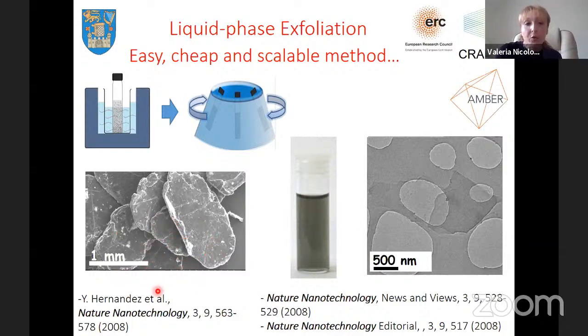So what we were capable of doing, and this goes back to my first postdoc work, was really applying everything we had learned for my PhD thesis. We had learned it for carbon nanotubes, but we applied it to layered graphite. We took commercial graphite flakes, nice and thick, and we could select a range of different organic solvents, which were very common, but were interacting very, very well with the material. And then by using sonochemistry, a simple sonic bath or sonic tip, we were capable of agitating this dispersion, allowing the solvent to interact with every single layer in the layered crystal, and then take it apart basically and induce the exfoliation in that way.